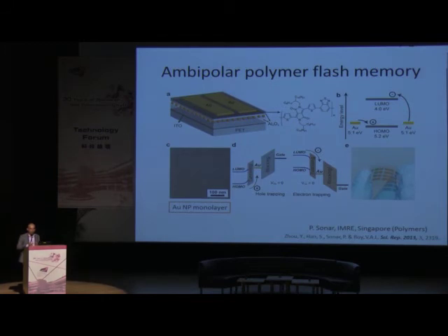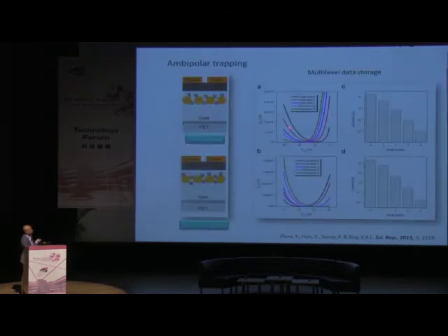So why do we need a balanced transport layer? The reason is, okay, if I trap electrons, then I have a 1 volt memory window. If I can trap holes as well, 1 plus 1 is a simple calculation, so twice the memory window. So with a balanced semiconducting layer, this metal nanoparticle has the capability to trap both electrons and holes. So if you see these devices, they work in ambipolar mode, trapping both holes and electrons.